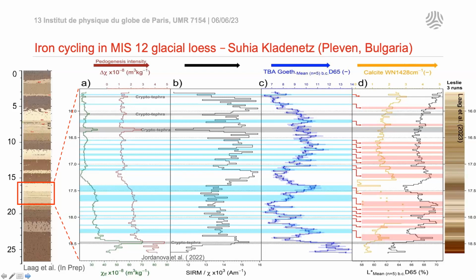The blue data is DRS, so diffuse reflectance spectroscopy, goethite concentration or goethite content results. Again, for sake of time, I'm not going to go in, but if you have questions, we can go through that afterwards. And then on the right-hand side, we have also from the DRS data, in black, the lightness parameter. So as lightness increases, the color is lighter. Lightness generally changes with organic matter. As you have more organic matter, darker colors, less lightness. And in yellow is attenuated total reflectance Fourier transform infrared spectroscopy, and from that type of data you can extract calcite content, which is what was done.